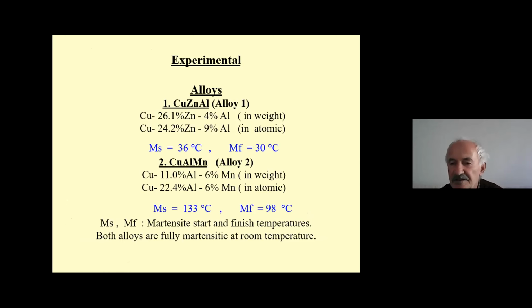These are the basic terms and definitions related to the shape memory effect. Experimental studies were performed on two copper-based shape memory alloys. You can see the chemical compositions of the alloys, and these compositions were selected in the beta phase regime of the material. Also, martensitic start and martensitic finish temperatures are above room temperature. Both of the alloys are completely in the martensitic state at room temperature.